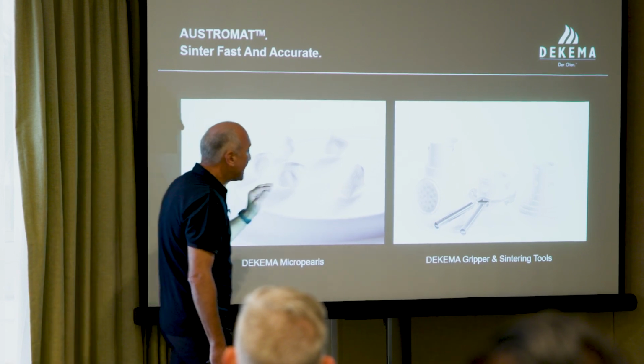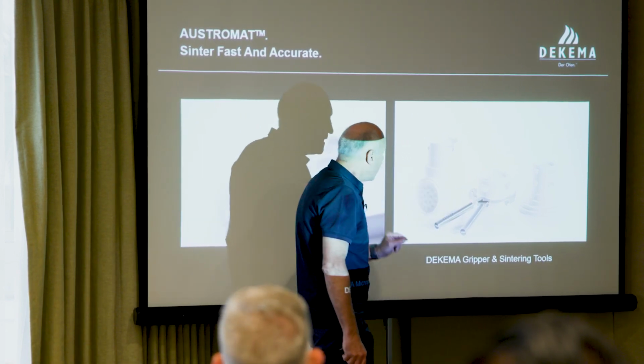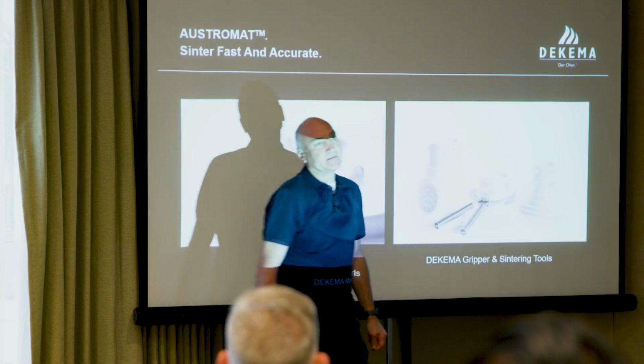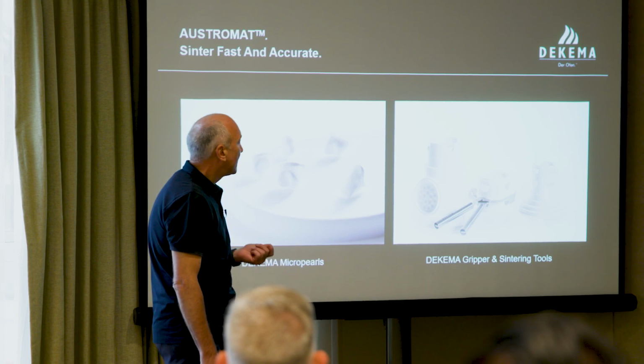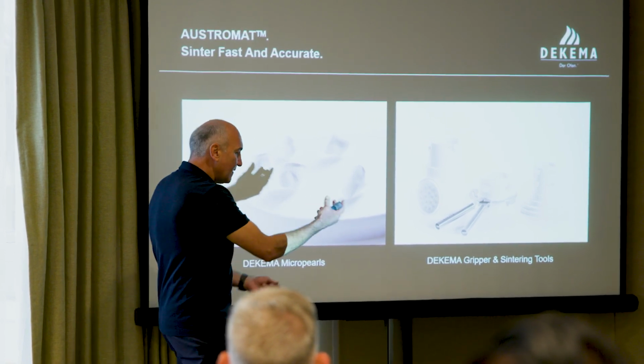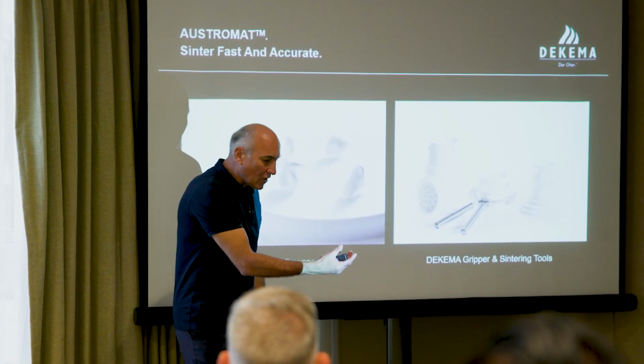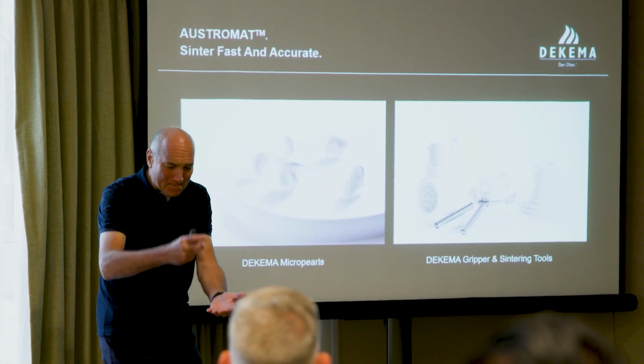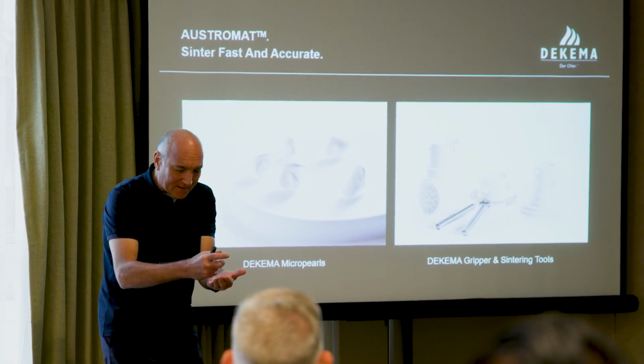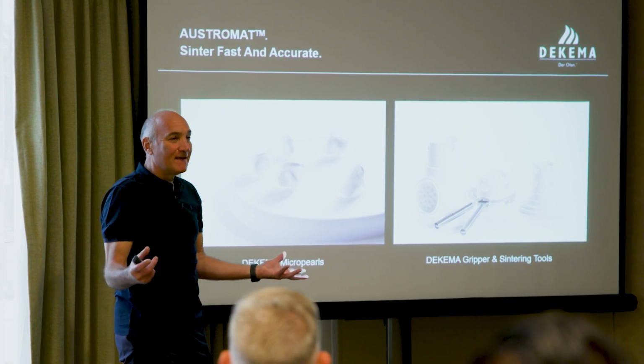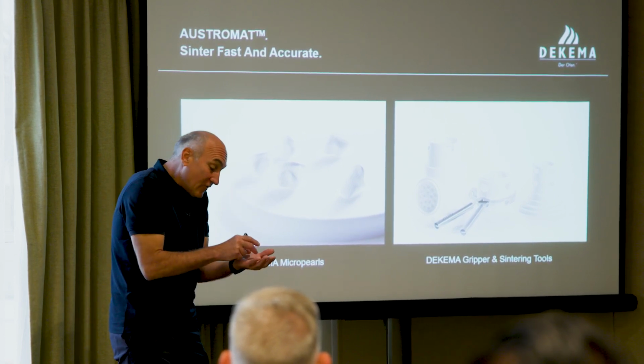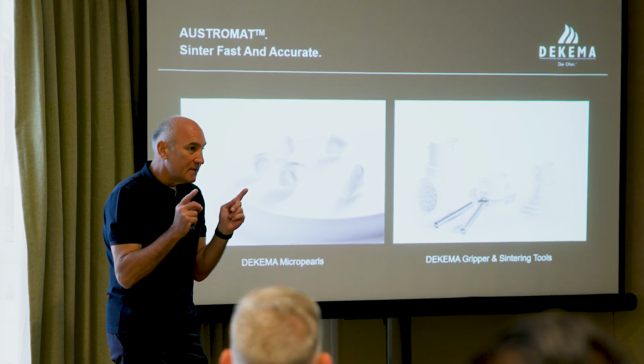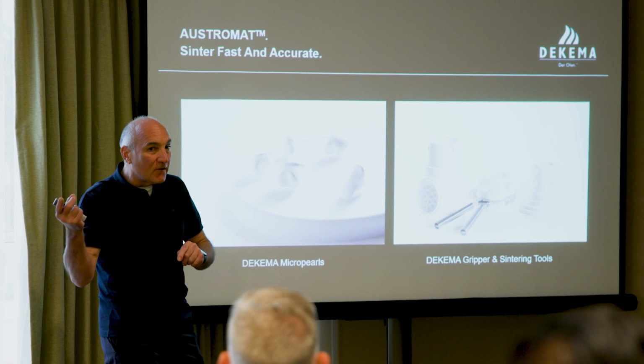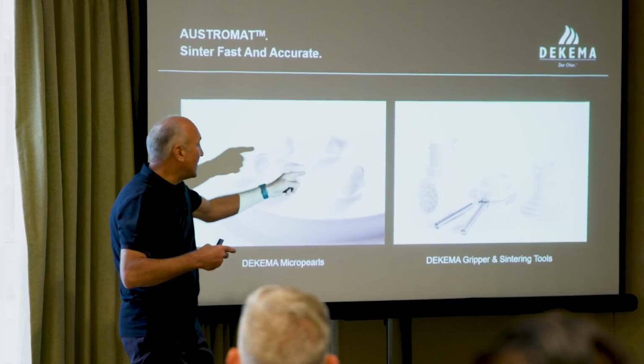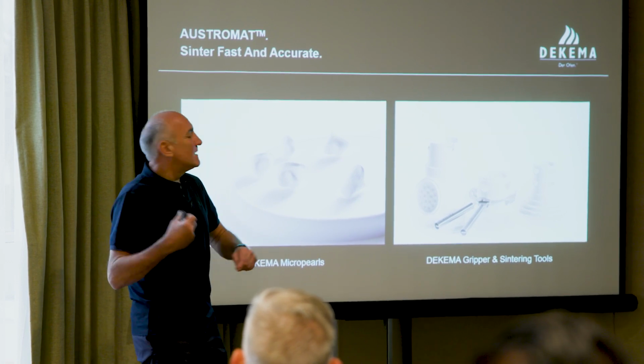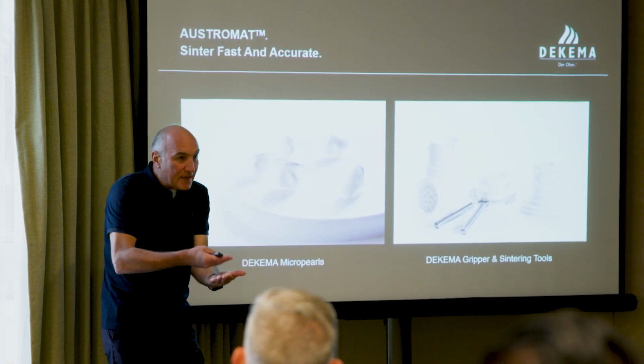Okay, let's come to this first. And then I talked about the right tools. If you have the right tools, you don't remove these rings. But most of the people don't bother. You have a metal plate. You use our plate with the zirconia on top. It's hot. Remove it and put it on a metal plate. It's thermal shock for everything. And what you then produce is micro cracks inside the plate, which you don't realize at that moment, which you realize in one of the subsequent sintering cycles. So you think this plate was breaking during sintering, but basically it was already breaking when you put it in thermal shock.